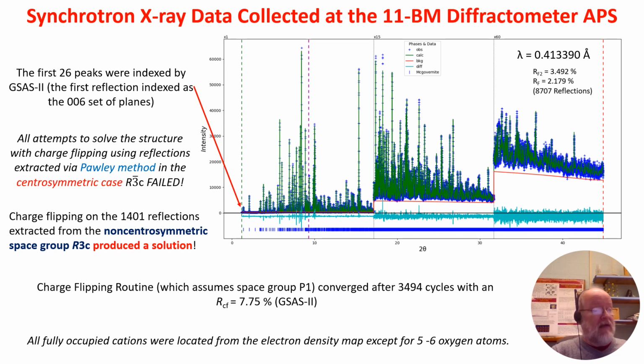Couldn't be done. Now, what's going on here is it's not in the charge flipping routine that we had the trouble with the center symmetry versus non-center symmetry, because charge flipping just assumes P1. It doesn't care. It's with the extraction. When we used the Pawley extraction and pulled out the centrosymmetric structure intensities, it didn't solve correctly. When we did the non-centrosymmetric, it solved correctly.